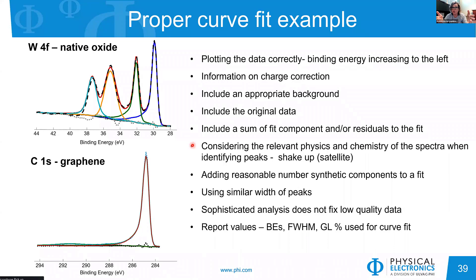Here is a summary slide for a proper curve fit. You need to provide how you charge corrected, include appropriate background, show original data not smoothed, include your mathematical reproduction and residual. Don't forget to include all spectral features discussed. Use a reasonable number of components with reasonable shape driven by your instrument settings. Data quality is primary, and then your interpretation drives the quality of that interpretation. In supplementary information, provide all values so other scientists can reproduce and use that information.